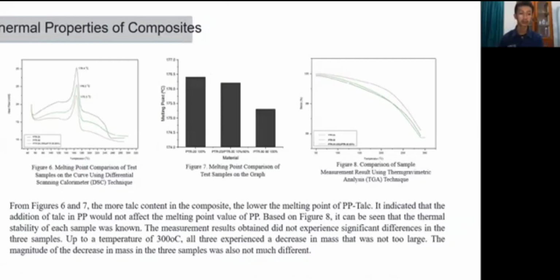Thermal properties of the composite. From figures 6 and 7, the more talc content in the composite, the lower the melting point of PP talc. It indicates that the addition of talc in PP will not affect the melting point value of PP. Based on the figure, it can be seen that the thermal stability of each sample was known. The measurement result did not show significant difference in the three samples. Up to a temperature of 300 degrees Celsius, all three experienced a decrease in mass that was not too large. The magnitude of the decrease in mass in the three samples was also not much different.